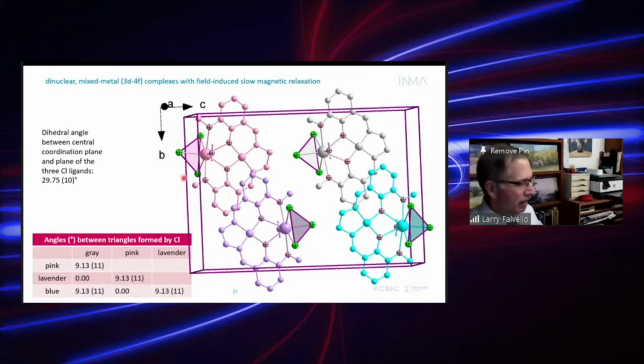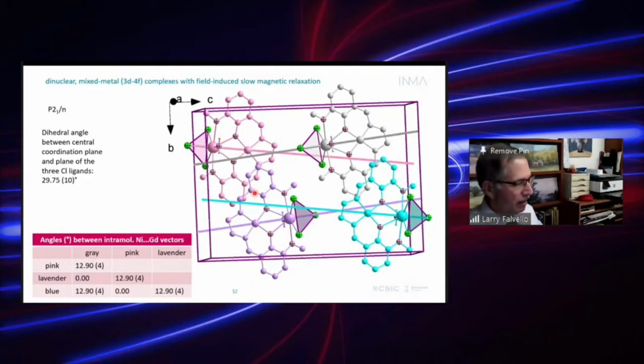The angles between these planes are either 0 for some pairs of molecules or 9 degrees for others. So even then, now it's only 9 degrees, but we're still losing information if we measure the single crystal with respect to what we would get if we could measure, hypothetically, a single molecule. We can argue that it's still better than what we get measuring a powder. And of course, for a single crystal, typically we need a bigger sample.